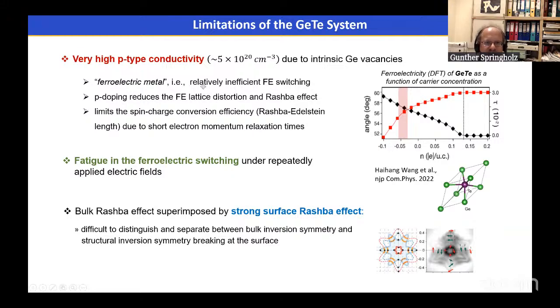So this high conductivity also makes the ferroelectric switching rather inefficient. This hole doping also reduces the Rashba effect and ferroelectric distortion, as shown in these calculations. So if the system goes from n-type here on the right-hand side to p-type, the sublattice shift decreases and the system goes towards the cubic phase, where this rhombohedral angle would be 60 degrees. So this in total limits the spin charge conversion efficiency, and this is one of the limitations of the system.